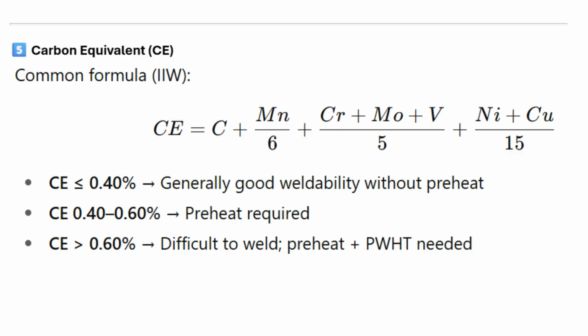Now, you see, it is not only carbon that has influence; there are many other alloying elements which also have influence on weldability. So there is a concept of carbon equivalent. Carbon equivalent includes the influence of other elements. Manganese, chromium, molybdenum, vanadium, nickel, copper, all of them have some influence. The formula for carbon equivalent is C plus Mn by 6 plus (chromium, molybdenum, vanadium) by 5 plus (nickel plus copper) by 15. And if the carbon equivalent is less than 0.4, it is quite good in weldability. So 0.4 and below carbon equivalent is good for weldability.